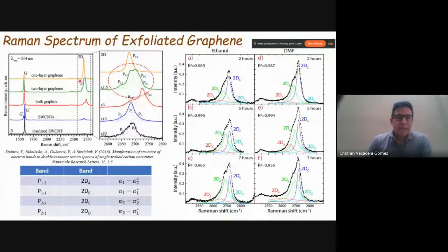Before, in this work, you can see here, for example, the Raman spectrum for 1-layer graphene or single-layer graphene, the same thing for 2-layer graphene or bilayer, and bulk graphite, and also the Raman spectrum for the carbon nanotubes, but it's not the focus of these explanations. Okay, but if we analyze the 1-layer graphene, maybe the question is why we didn't do any fitting on this? Because this is a very narrow peak, the 2D band. So this can be fitted just by using 1 Lorentzian function. If we analyze now the graphite, like in our previous sample, we have 2 Lorentzian functions that can be used to fit the graphite. But if you have 2-layer graphene, tri-layer graphene, and 7-layer graphene, you can fit your 2D band with 4 Lorentzian functions.